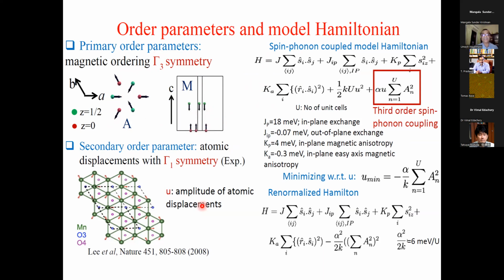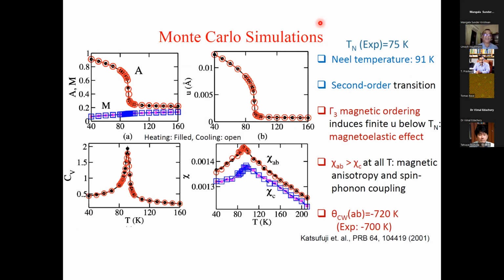And then those energies are fit to the model Hamiltonian, which is a spin-phonon coupled model, where the phonons are also coupling in the third order with spins. Okay, and all these parameters we calculate from first principles. And then this model Hamiltonian is simulated in Monte Carlo simulations. And indeed, in this case, we were very successful. The Néel temperature experimentally is 75 Kelvin. Our simulations give about 91 Kelvin. We find it's a second order transition with specific magnetic ordering, which is in agreement with experiment.